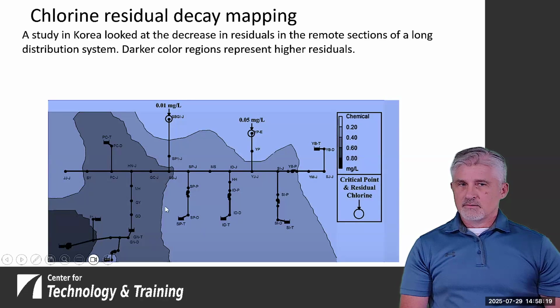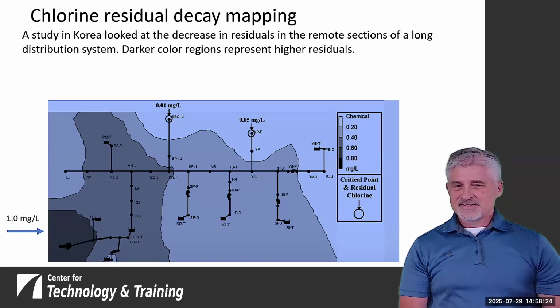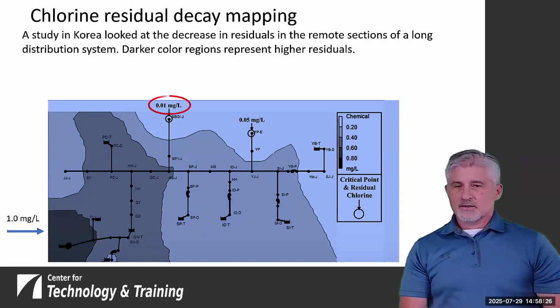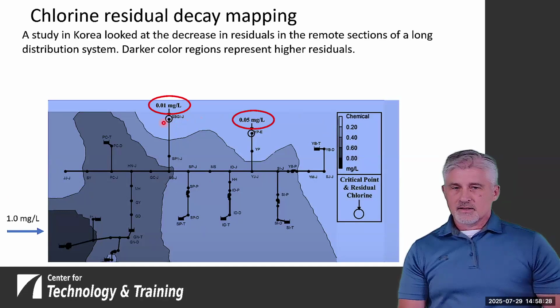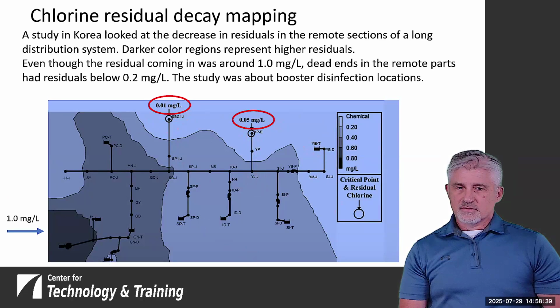So it comes in here, and we've got residuals of 0.01, 0.05. Even though the residual is coming in around 1, dead ends in the remote parts had residuals below 0.2. So that's one, as we mentioned, we want to stay above 0.2.